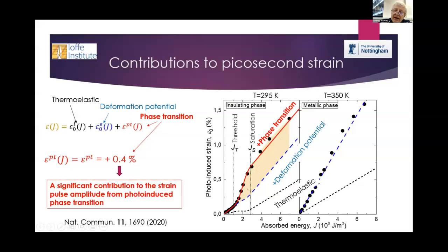And then what is coming else, it is just due to the phase transition, due to the changing of the lattice, due to the rapid changing of the lattice, so that the strain pulse is injected into sapphire substrate. And you see the fraction of this is quite big.